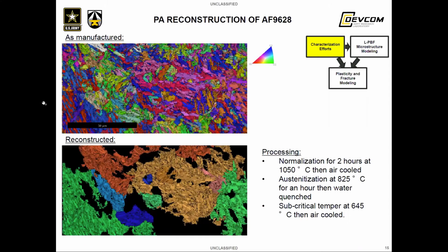So here, a similarly wrought and heat-treated sample of AF9628 has been reconstructed, or rather, the reconstruction was attempted. This sample has a lower austenitization temperature and was likely not completely re-austenitized. This is evidenced by the large reconstructed austenite regions with very irregular boundaries, and then smaller austenite regions within those regions with more regular boundaries, kind of embedded in the larger austenite reconstructed regions.